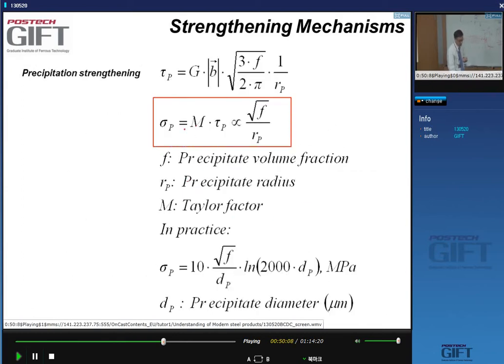So the precipitation strengthening theory gives you this kind of equation. If you're interested in using theory to predict what kind of strengthening you get in, for instance, experimental steel, this is a good formula to use, where sigma p is the strengthening effect of precipitates with a diameter dp and a volume fraction f.